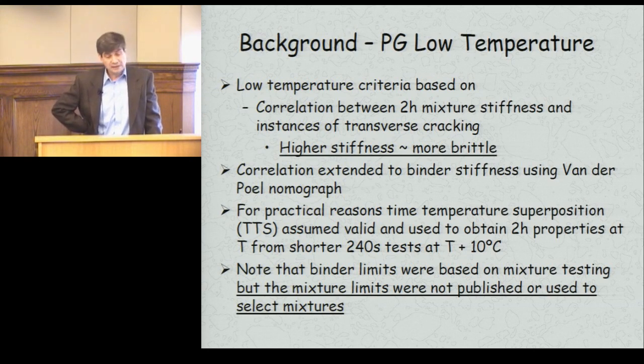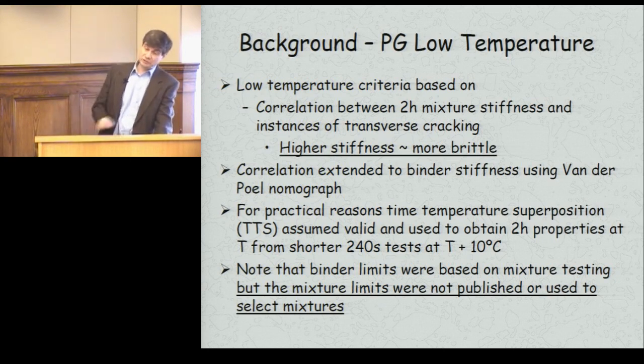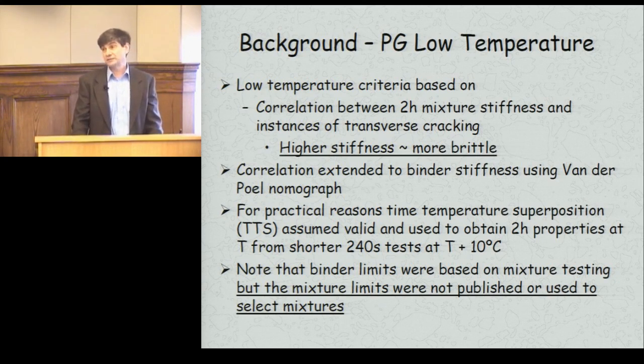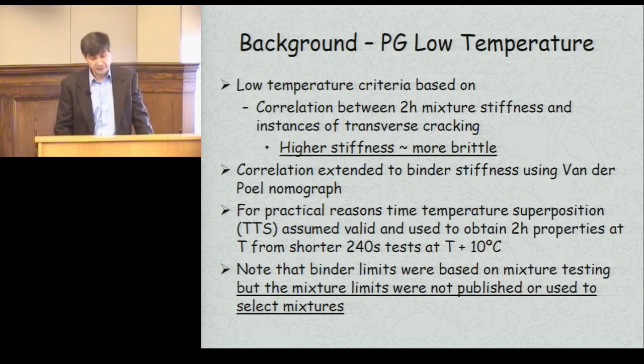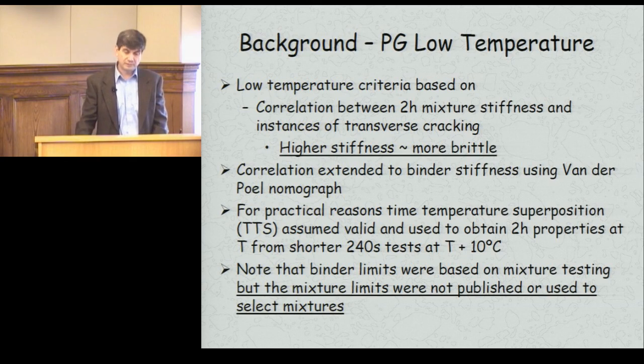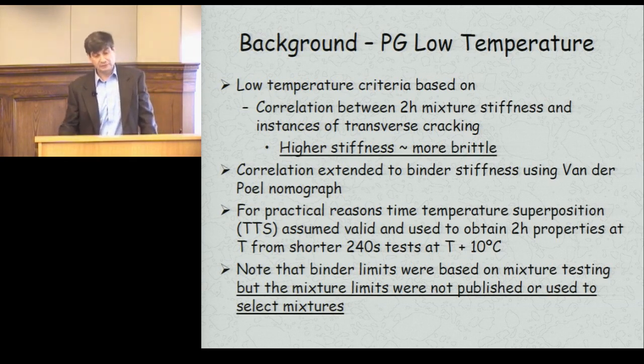Basically, they found out there is a correlation between the mixture stiffness measured after 2 hours of loading time and instances of transverse cracking in asphalt pavements. They had the idea that if you have a material that is stiff, that means it is also brittle, which at that time probably was not too far from reality, because we were using plain asphalt binders - no modifiers, no recycled asphalt, no newer technology. So that probably was relatively valid. If you had high stiffness, that automatically meant brittle material, which most likely would crack.